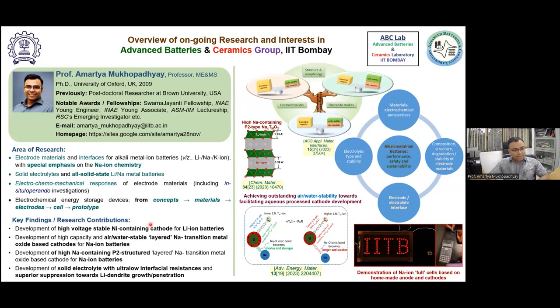We have also had some contributions on the nickel containing layered transition metal oxide cathodes for lithium ion batteries, and also some good contributions on the solid state lithium based cells, especially the interface between the solid electrolyte and the anode and the electrode, as well as how to make the solid electrolyte air and water stable so that one does not need a dry environment to handle the solid electrolyte, which is what the next generation battery systems are looking at, and how to prevent or suppress the dendrite penetration to a significant extent.